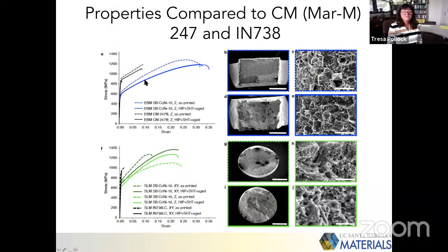And so you can see the blue curves here are the electron beam printed cobalt nickel alloy. And we have, even in as printed form, the dotted line, very high ultimate strength and very high tensile ductility. And if one does best effort on printing that 247 alloy, you might get something of the order of 5 or 7% tensile ductility. This is the SLM material.